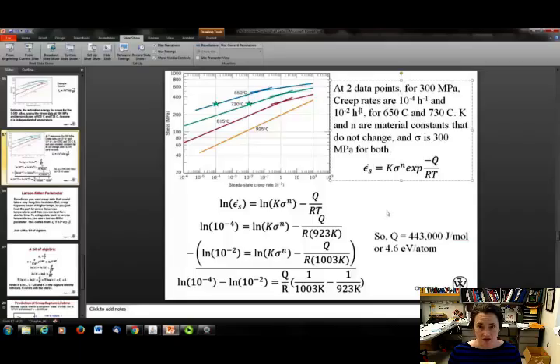So from this, I've got basically two equations and two unknowns, right? I know my values of my creep rate. I know my values of my temperature. I don't know my K sigma to the N bits, but since I have two equations, I can just subtract those two equations and then that constant drops out. So I end up with the natural log of 10 to the minus 4 minus the natural log of 10 to the minus 2 equals Q over R times 1 over 1003 minus 1 over 923. Okay, and I solve this equation, and I get my Q there, plugging in for the known value of my gas constant, R, 8.314 joules per mole Kelvin.